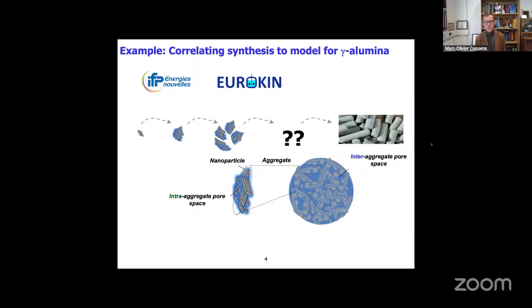And so the question is often how you then really relate the original nanoparticles with the eventual material. And that's important to be able to predict transport properties, to predict also diffusion and reaction when this material you see here on the right is used as a catalyst or catalyst support all the way for industrial processes. For example, gamma alumina is used as a support for platinum and platinum-rhenium in catalytic reforming, used in refineries at enormous scales around the world. So clearly, this is one way. Can we understand and correlate synthesis to models?